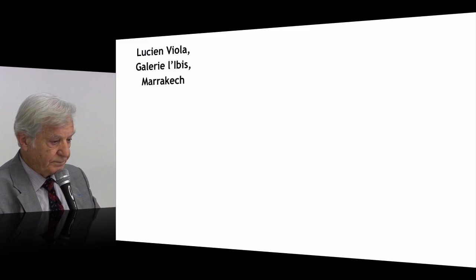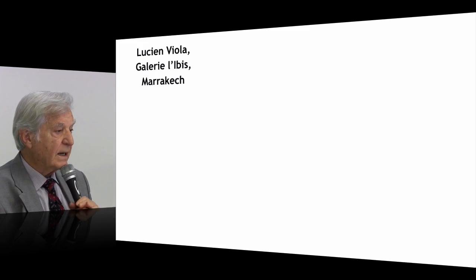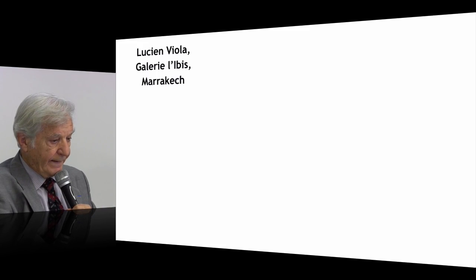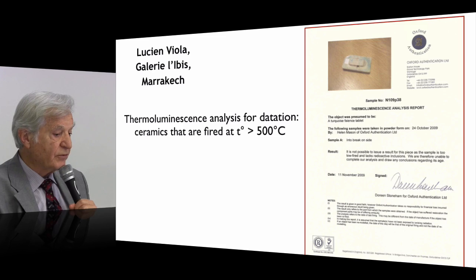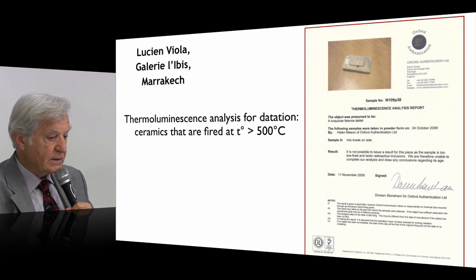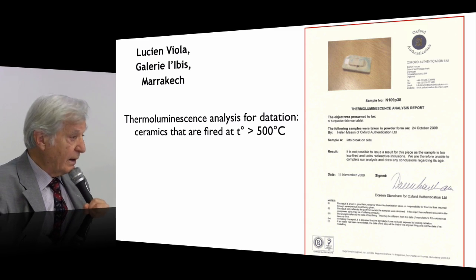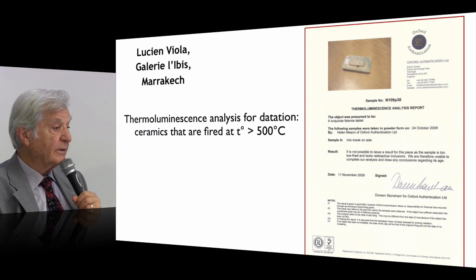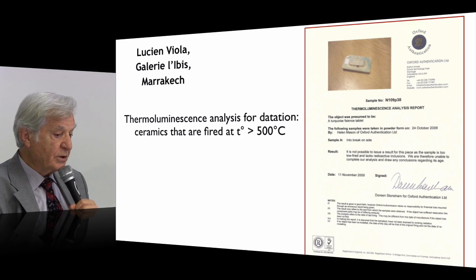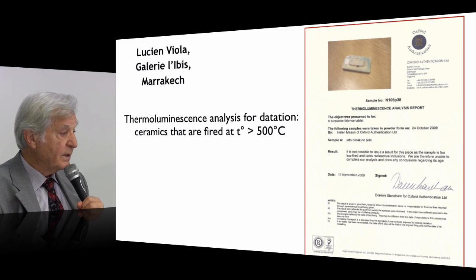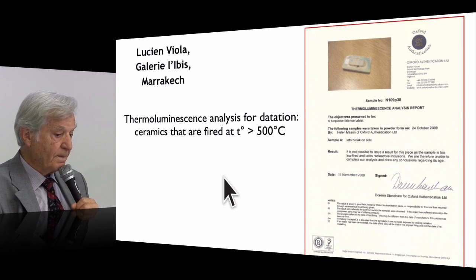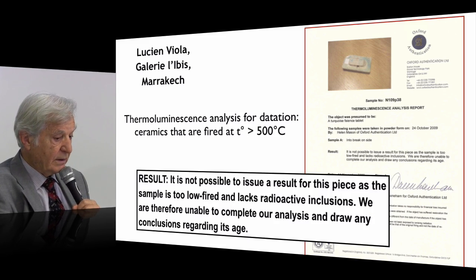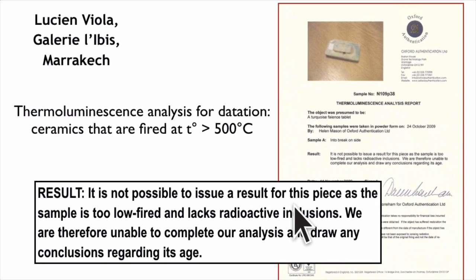We received some years later a mail from an antiquarian that has a collection of these tiles, and he asked a renowned laboratory in Oxford to make thermoluminescence analysis for dating of the ceramic that are supposed to have been fired at a temperature of 800 degrees C. The thermoluminescence analysis requires that the ceramic has been fired at least over 500 degrees C. So they made the analysis in Oxford, and this was the answer: "It is not possible to issue a result for this piece as the sample is too low fired and lacks radioactive inclusion. We are therefore unable to complete our analysis and draw any conclusion regarding its age."